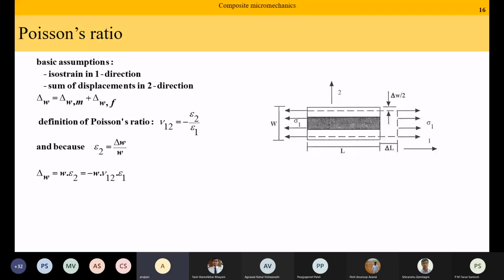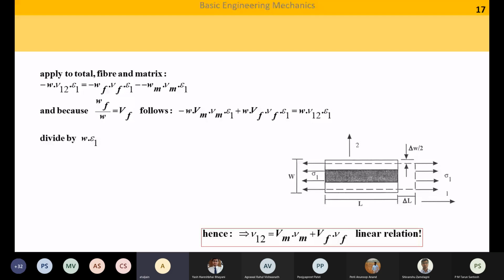And then, taking into account these two assumptions, isostrain in one, sum of displacements in two, and noting that E2, the strain in the two direction, is delta W, which is the change in length in the two direction divided by W, I can say delta W is minus W into nu 1,2 into E1. And we are saying that in the two direction, it is sum of displacement. So I am saying the displacement of the composite is equal to displacement of the fiber plus displacement of the matrix. I am putting a minus sign because if I'm applying tensile load in the one direction, everything should be negative.